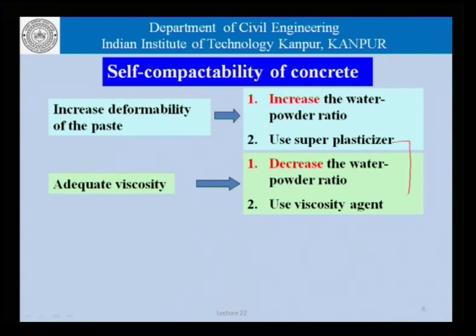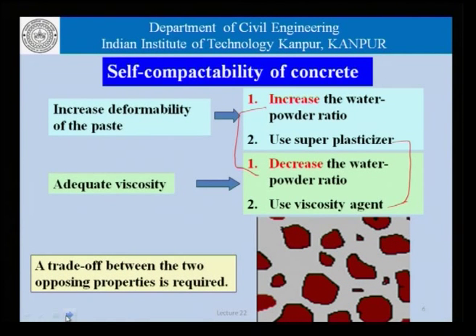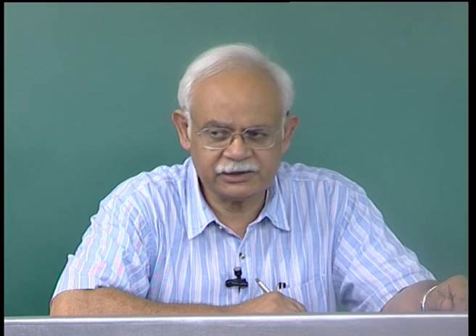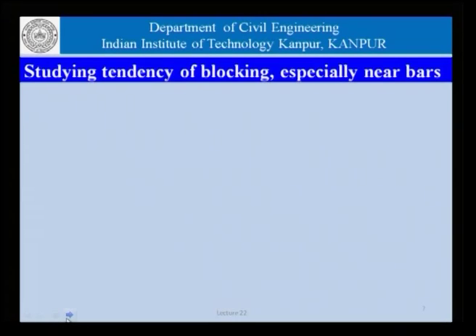So, these two are the chemical admixture route, or this is the physical route where we are trying to change the water powder concentration in the system. Now, as far as the self-compactibility of concrete is concerned, or the high flowability of concrete is concerned, we are really looking at a trade-off between these two opposing properties. One of them requires the paste phase or the liquid phase to be more deformable, whereas the other requires the same phase to be less deformable. So, it is basically a trade-off.